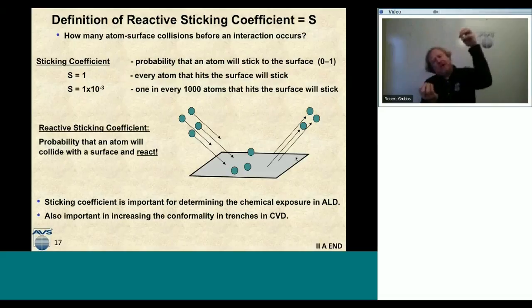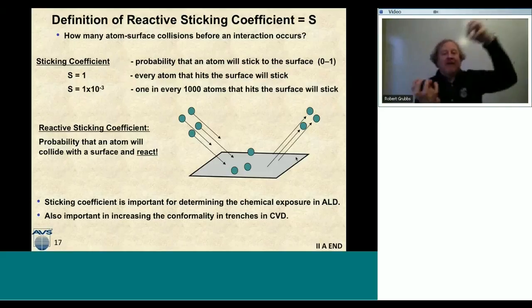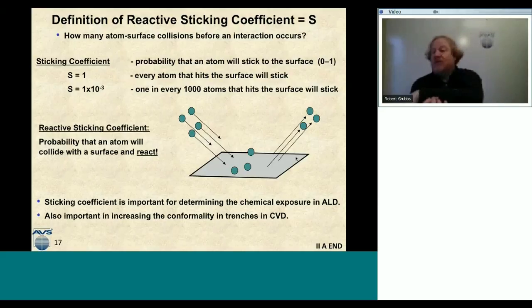But some fraction of those colliding molecules or atoms will actually stay on the surface and be stuck in that physisorption well. If they come down to the surface, adsorb in the physisorbed well, and then go to the chemisorbed well, which is what we want in ALD, then it's the reactive sticking coefficient. That's the probability that an atom will come down onto a surface and then actually react to form a thin film. Since the sticking coefficient is a coefficient, it's between the value of 0 and 1.